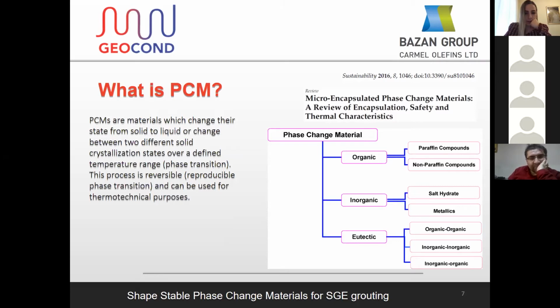There are different families of phase change material, differing in their chemical nature. They can be organic, inorganic, and eutectic. Each family has its advantages and drawbacks, and the relevant ones for us are organic phase change materials, which are highly crystalline compounds, covering a broad range of melting and crystallization temperatures and having latent heat of their transitions close to 200 joules per gram. More specifically, for this project, we used organic PCM.